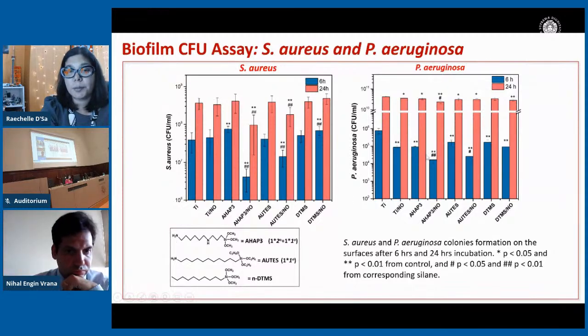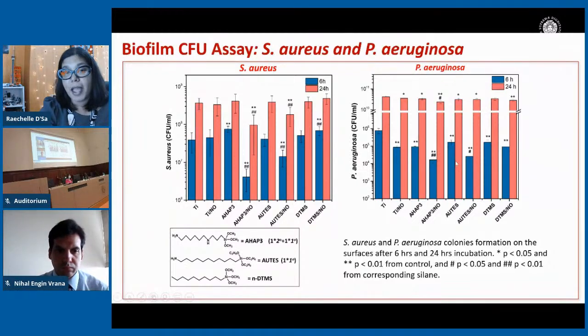When we look at Pseudomonas aeruginosa now, what we find is that Pseudomonas aeruginosa is notoriously more difficult to kill than Staphylococcus aureus, but we find that the same trend exists. After 6 hours, the AHAP surface has a 0.8 log reduction in the amount of bacteria, and the AUTES surface also has a 0.8 log reduction in the amount of bacteria for the nitric oxide surface compared to the silanized surface.